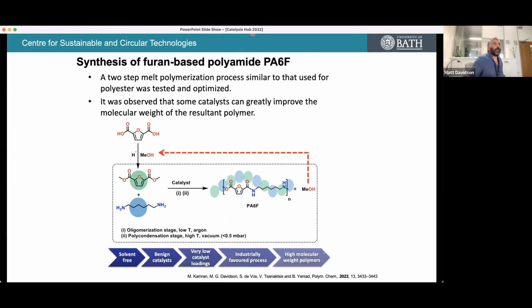So we thought we'd have a look at these based on work that we've done for making PEF using titanium catalysts. What Cameron did was take this diamine and the methyl ester of FDCA and undertake a two-step melt polymerization process, which is something that we and others have developed to make PEF in the past using similar catalysts. We're using titanium-based catalysts, and we can use very low catalyst loadings. Of course, this is a melt polycondensation, so it's potentially an industrially favored process.